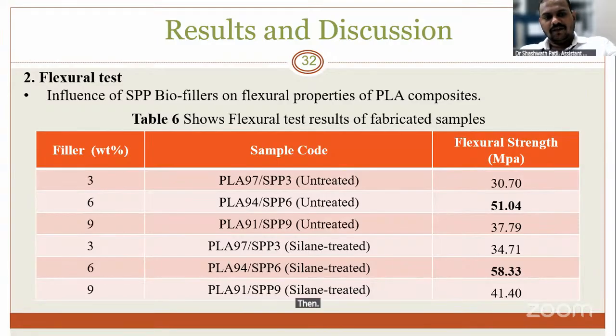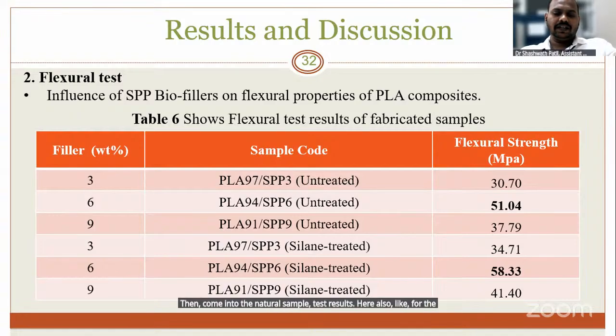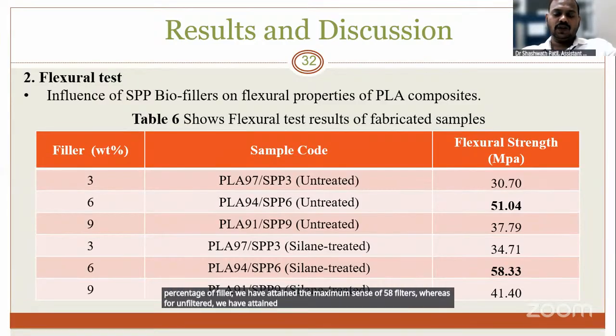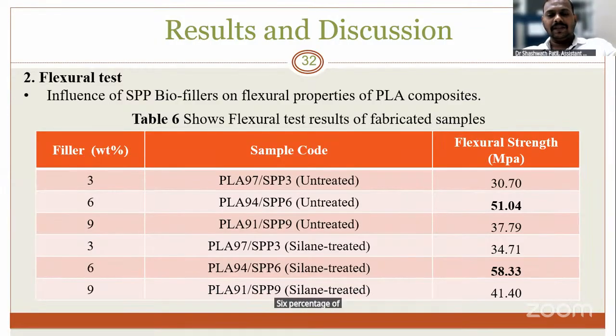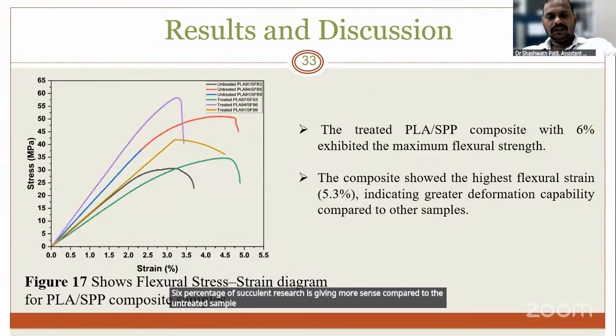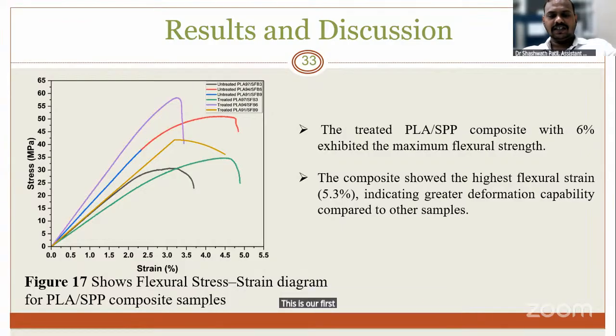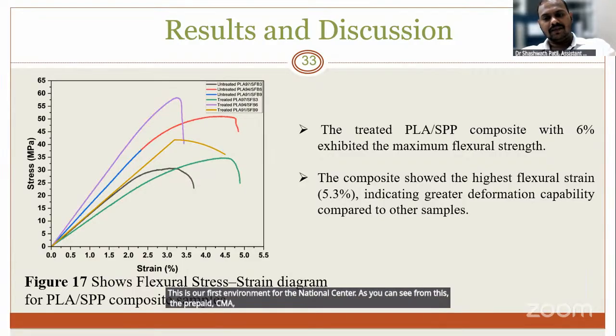Then coming to the flexural test results, here also for the 6% filler we have attained the maximum strength of 58.3, whereas for untreated we have attained 51.04. Overall, the 6% silane treated samples give more strength compared to the untreated sample. This is a strain diagram for the flexural strength. As you can see, the treated PLA composites with 6% show the maximum flexural strength.